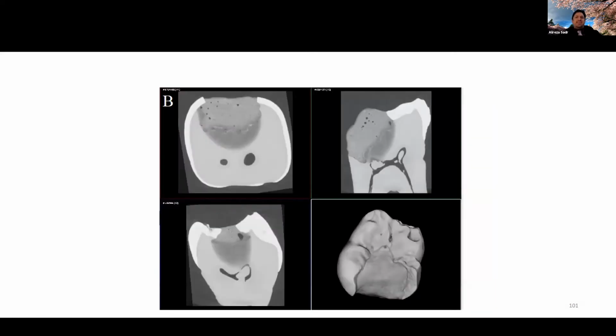So here what we did, we applied the silver diamine fluoride over just cavitated lesions, advanced by ADA criteria, advanced lesions. We applied silver diamine fluoride, and we reapplied after 1 week in one group. We applied Glass Ionomer immediately in the other group, and then we applied Glass Ionomer after 2 applications of SDF in another group, and kind of looked at the reaction of totally infected dentin to the combination of silver diamine fluoride here and Glass Ionomer.